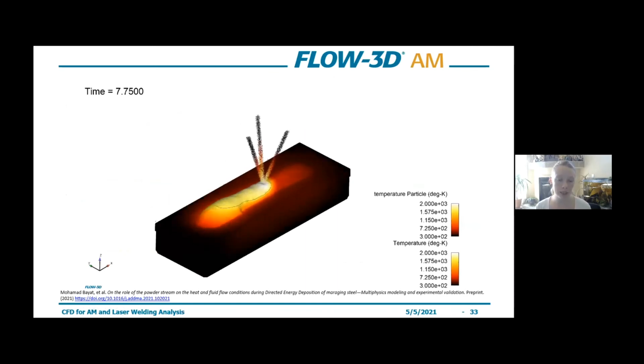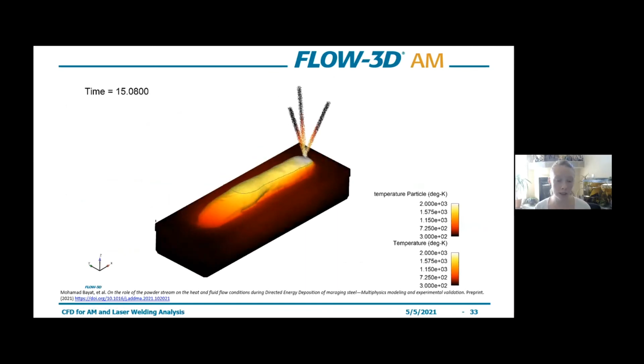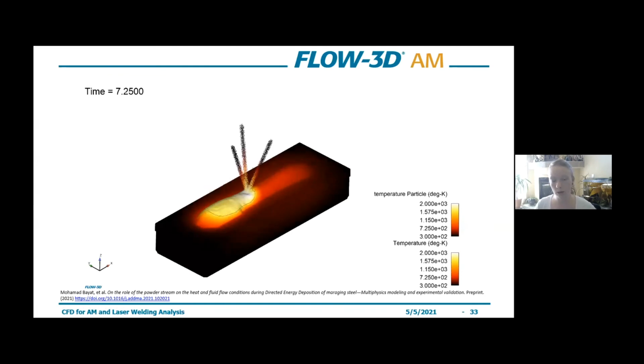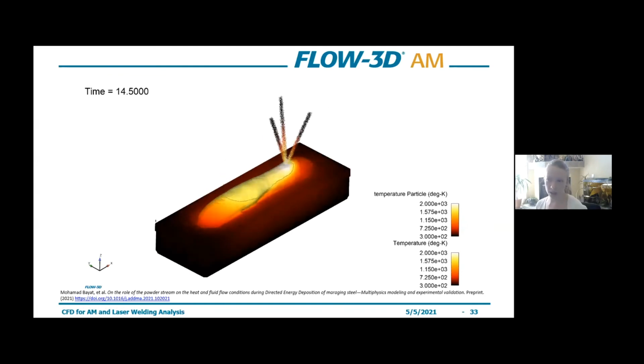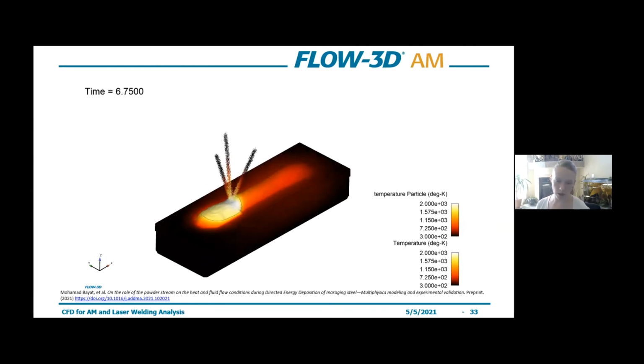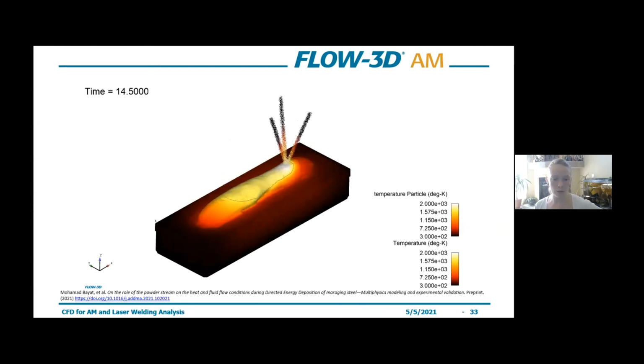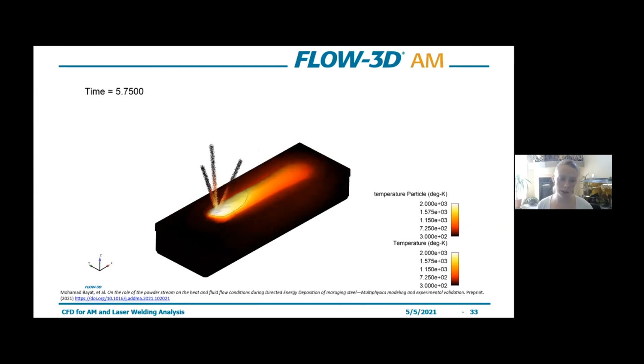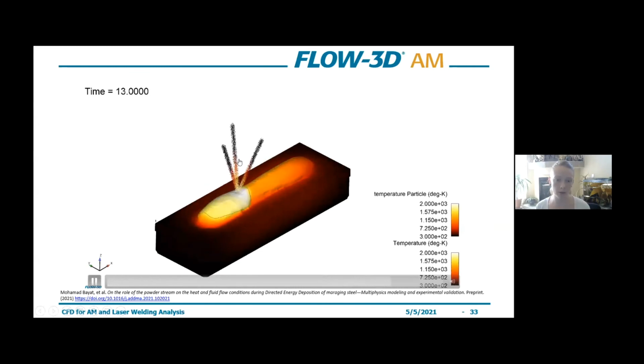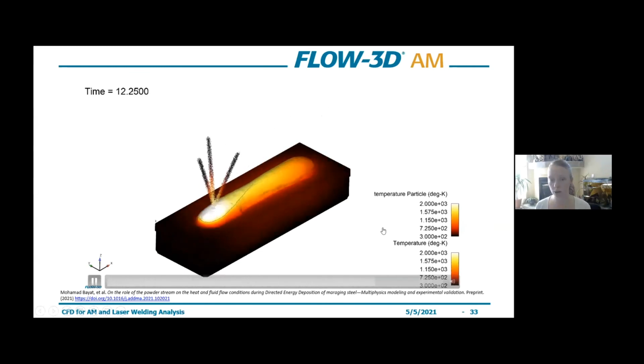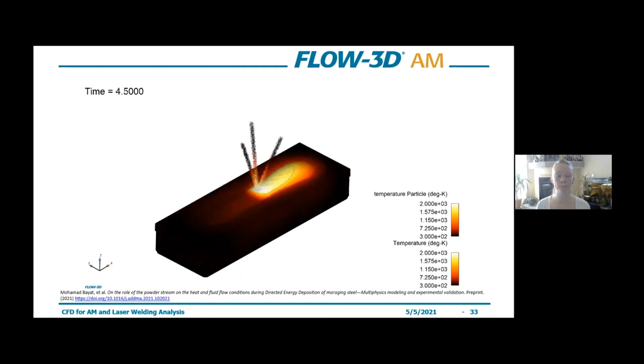So in this case, they did a few different layers. So you can see there's quite a bit larger domain size that you can achieve when you're doing a directed energy deposition. Plotting the temperature here, so you can see as the powder particles come down and are melted by the laser, you can see their temperature heating up.